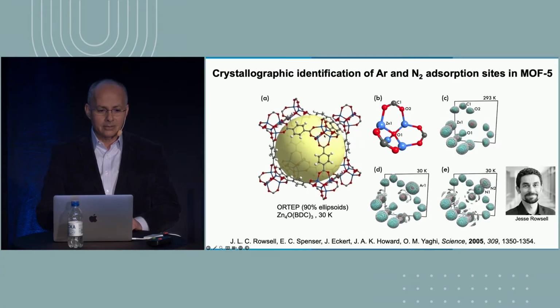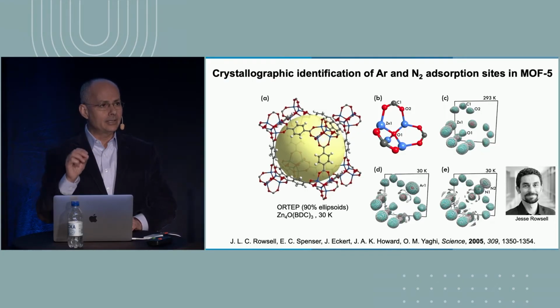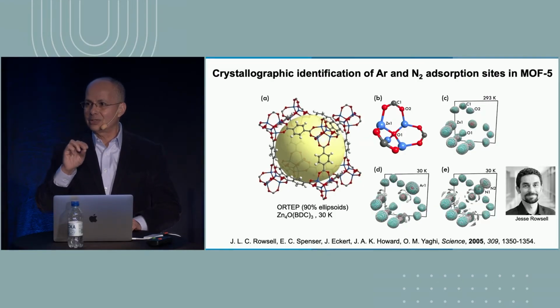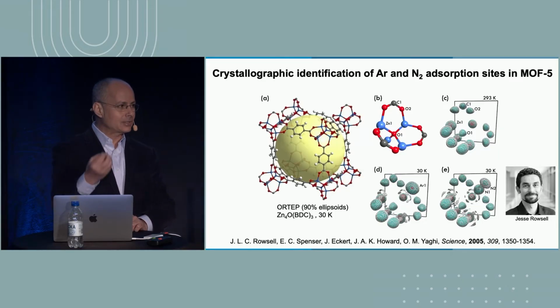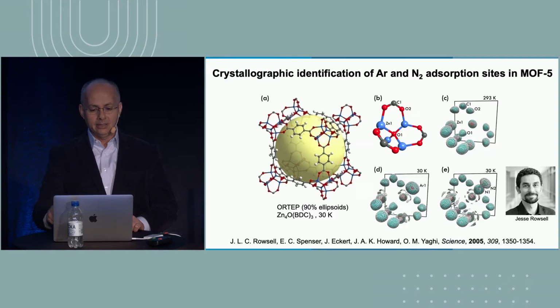So this is the crystal structure. We actually can see the crystal structure without any stuffing. And now to figure out why does it have a high surface area, we have to figure out where these gas molecules were residing in the structure, because wherever they sit, that represents the surface area onto which I can trap gases. So you see here, when I introduce argon, it sticks to this site, to the metal site, which are the corners. If I introduce nitrogen, it does exactly the same.